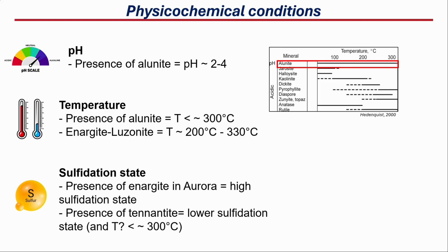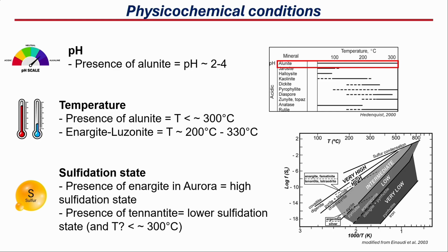So talking about temperature, again, presence of alunite can constrain the temperature, but also the presence of enargite and luzonite, if they are intergrown, those are used as thermometers and can be between 200 and 330. And if now we think about the sulfidation state of the system, enargite itself represents a high sulfidation state, but covellite is even higher, and we have that in the outer areas of Aurora. And also the presence of tennantite, which is not in Aurora, it's on the outer areas, can show us a lower sulfidation state and probably less temperature. So just to show this diagram, which is initially from Barton and Skinner, but modified from Einaudi, we can see that there is a slight boundary between the enargite and the tennantite sulfidation state.